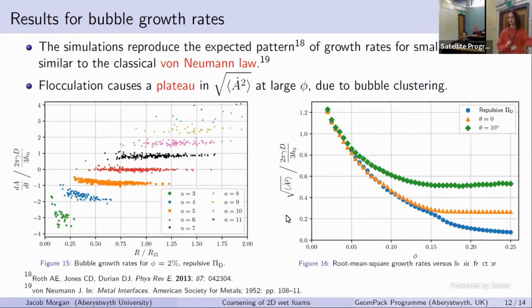So we wouldn't expect this to be quantitative for every foam. As an example, with the growth rates, clearly maybe it's trivial in this case because von Neumann's law should give the exact result. But in the Voronoi foam, using just the areas given by the Voronoi tiling directly, you see a compression, as in the realized part of the distribution of growth rates is narrowed in terms of radius, if that makes sense.